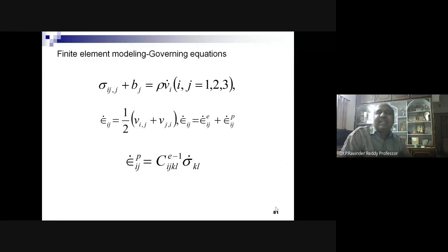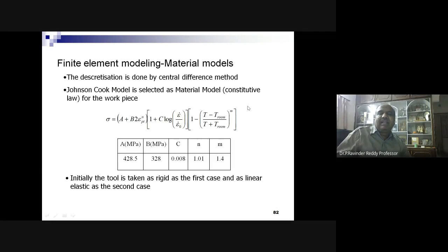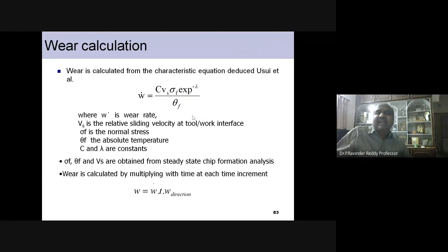And typically, the governing equations used for the constitutive relationships are those, and accordingly, the Johnson-Cook model is taken. The constants A, B, C, N, and M, the remaining are estimated from the analysis. And this is a wear rate which we can calculate, where C and lambda are constants, W dot is wear rate, Vs is the relative sliding velocity of the tool, sigma F is the normal stress, theta F is absolute temperature. The sigma F, theta F, and Vs are obtained from the steady state chip formation analysis. Wear is calculated by multiplying with the time at each time increment. Then you can calculate those.